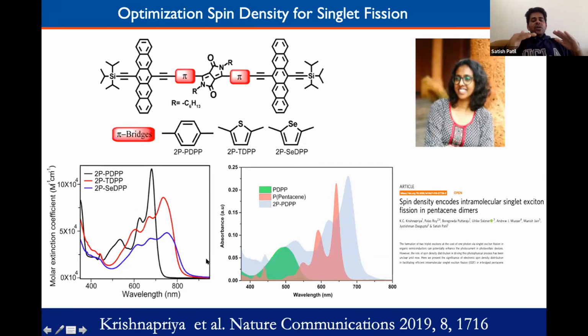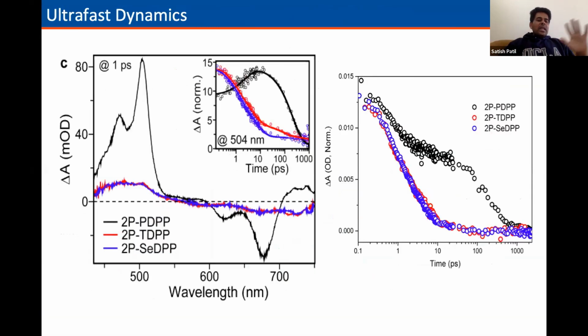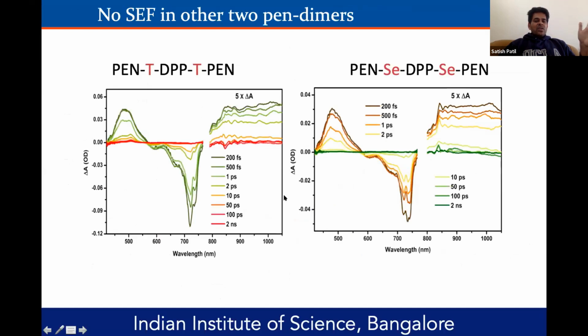That indeed tells you there is a strong coupling when you put thiophene and selenophene, because the bridge is very planar, whereas when you put a phenyl as a linker, essentially you twist the phenyl and then you have a blue shifted spectra. I will not describe the ultra-fast dynamics, which was done in collaboration with my friend at TIFR Mumbai. Interestingly, when we did ultra-fast spectroscopy, phenyl undergoes singlet fission, we see triplet signatures, whereas thiophene and selenophene do not undergo singlet fission.